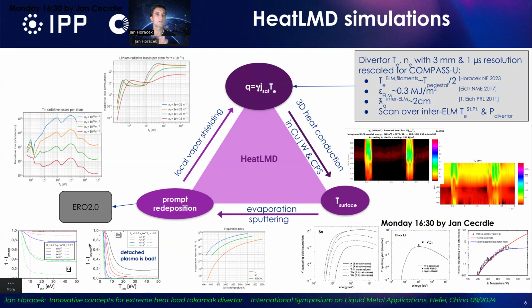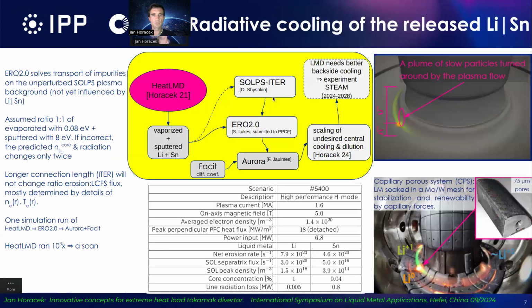It means that detached plasma really releases a lot of particles into the plasma, which is then put into the ERO code, which calculates how much goes into the plasma before, in fact, it's locally shielded using lithium and tin radiative losses just nearby the divertor target. Right. So what goes into ERO, the structure is shown here, as I said. We can run ERO only for one case because it's a heavy code. So this is the amount of lithium and tin going into the plasma nearby the divertor.